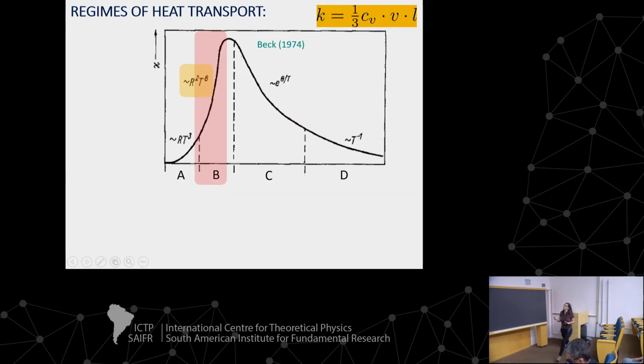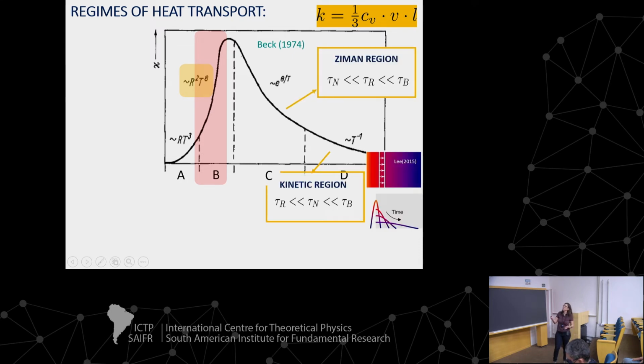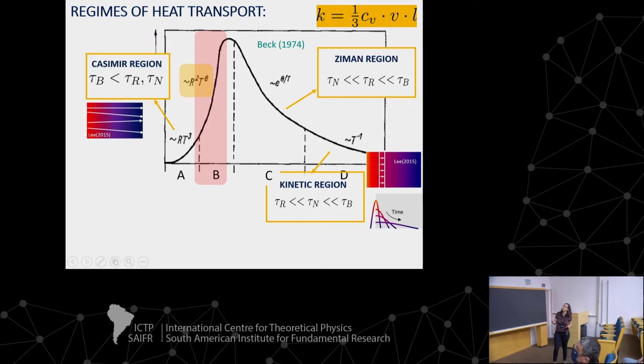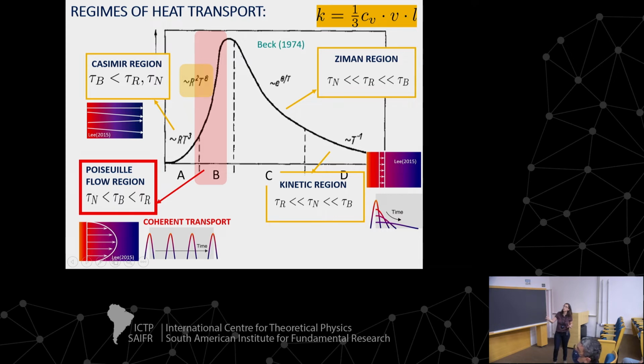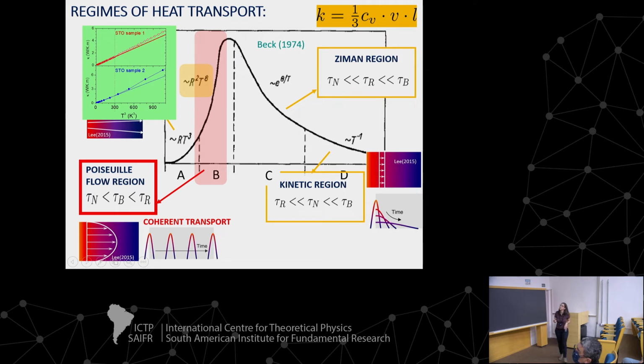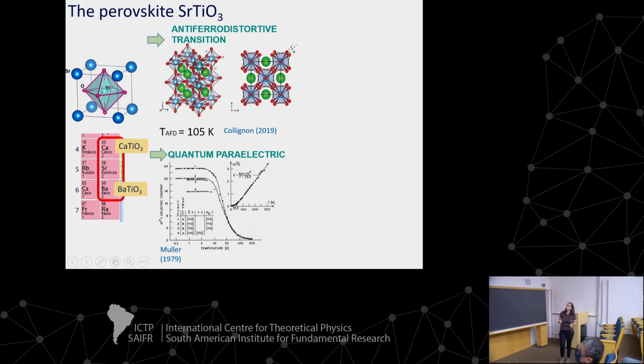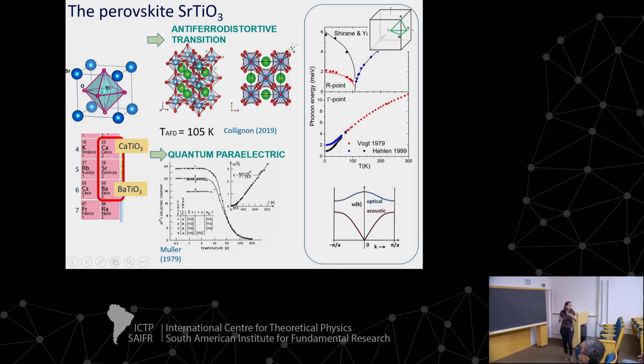Okay, just to summarize this very quickly, this is from the same work. This is the textbook thermal conductivity that we expect from a material. We have the different regimes depending on the different hierarchy of scattering times. This region is where we expect to find it, and this is what we have observed in STO, just to place it again there. But the question is then how can we understand the emergence of this regime in this material? If we go back to the beginning, this material has two prominent characteristics. One is the antiferrodistortive transition, and the other one is the quantum paraelectric state. These two have been observed to give rise to soft modes in the phonon spectra.